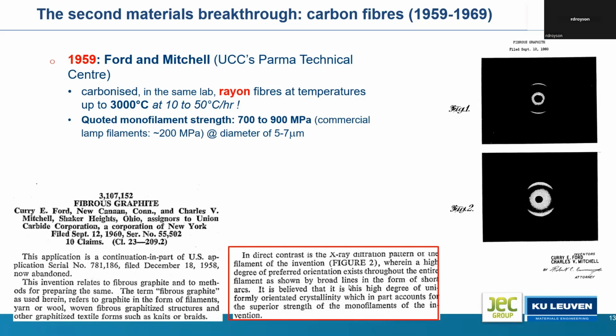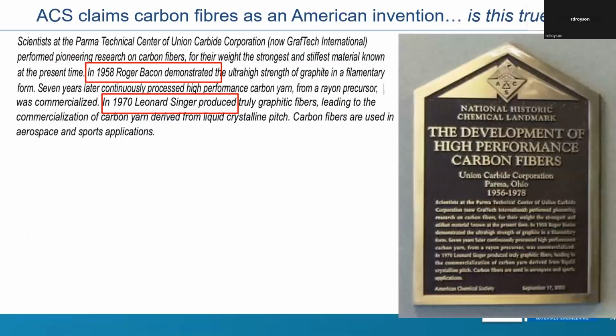You see it here in the text below that they measured that by X-ray diffraction, and they say that a high degree of preferred orientation exists throughout the entire filament. And it is believed that this high degree of uniformly oriented crystallinity in part accounts for the superior strength of the monofilament. So this is, as far as I could reconstruct, the first time that this link was made between the structure of the graphitic layers on one hand and the high mechanical properties on the other hand.